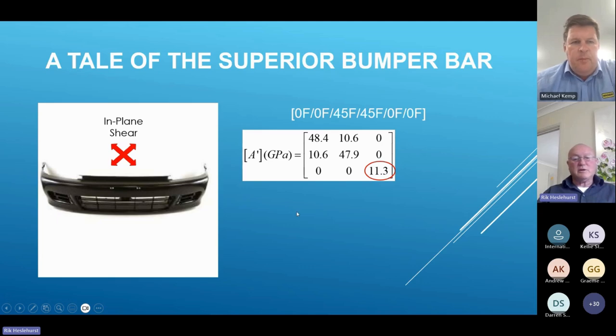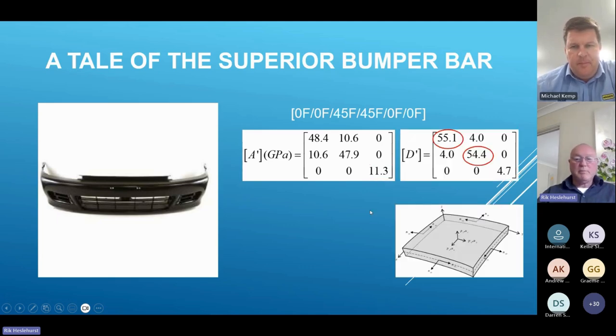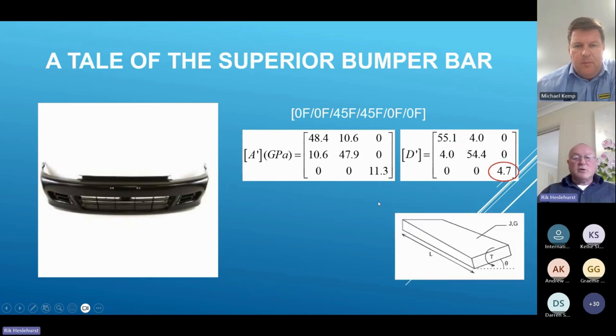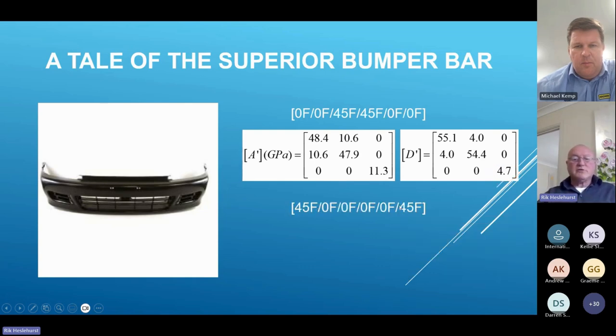Now, when you bend the bumper bar, bending it in plane and getting that bending deformation, the effective Young's modulus in the longitudinal direction, bending direction, is 55.1 and about 54.4 in the transverse. But look at that shear torsional resistance, 4.7. So they asked me what I could do. So I said, well, apart from a couple of minor details, change the configuration to put 45s on the outside. Remember, the title of the seminar is What's Inside Matters. So put the 45s on the outside.